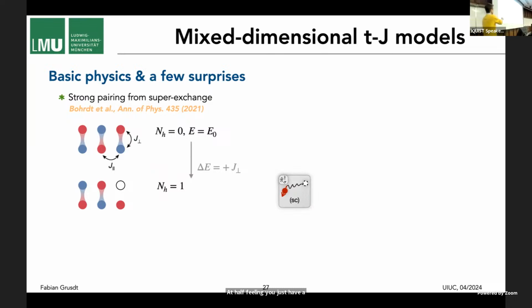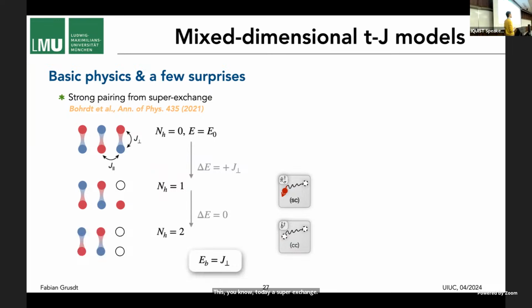Now, if you put a single hole in, what you form is one of these spinon-chargon bound states. It's basically a hole, and you break up a singlet. And that costs an energy, J perp, this interlayer super exchange, which is a nice energy scale. But then if you add a second hole, what you can do is you can just remove this spin here. And that way you basically realize the second type of excitation, that now it's a chargon excitation. It basically forgets all the information about spin. So it's a second type of meson if you want. And adding the second hole, you don't have to break up a singlet, right? So clearly this basically costs no energy, and therefore pairing is favored, right? So you get a binding energy of the two holes on the order of the super exchange energy.